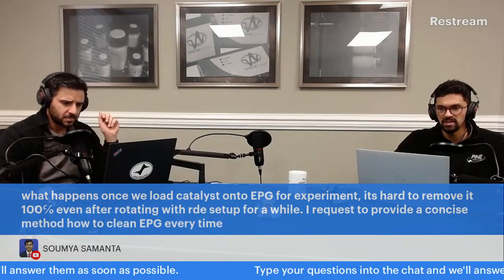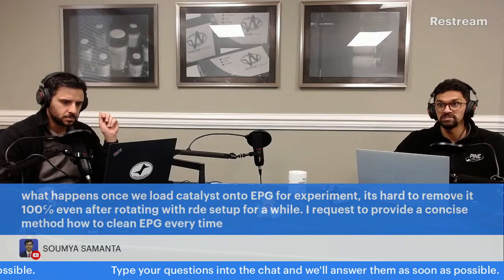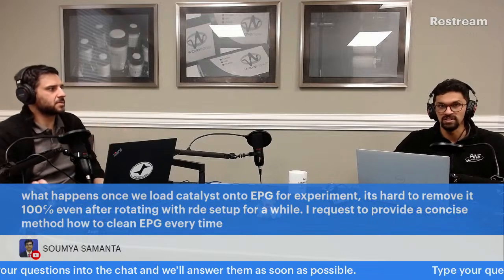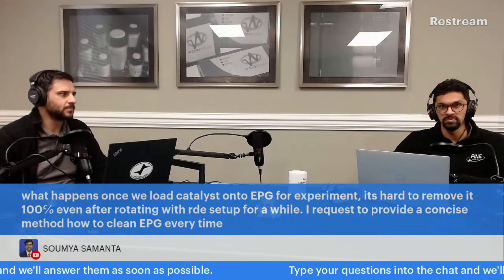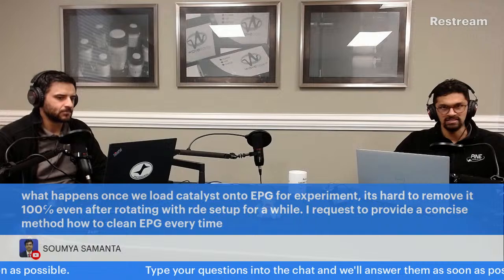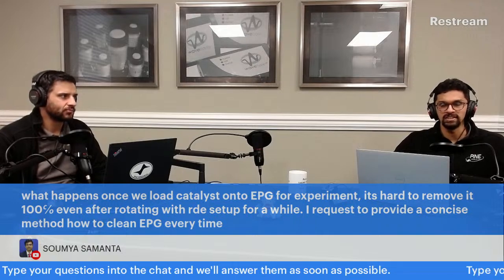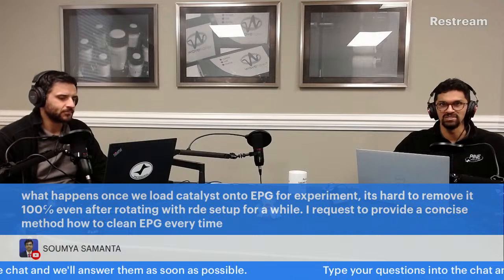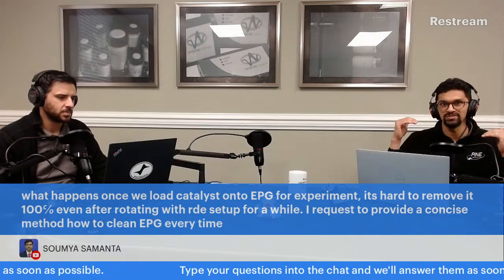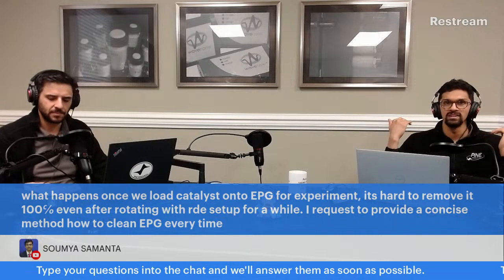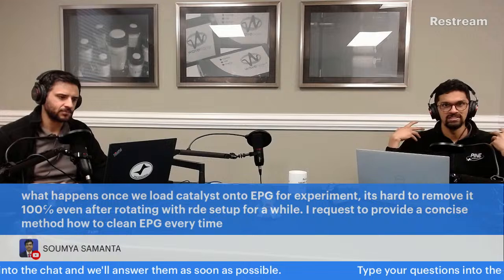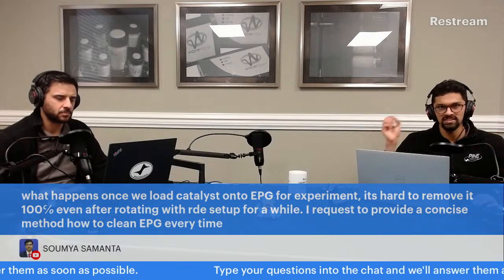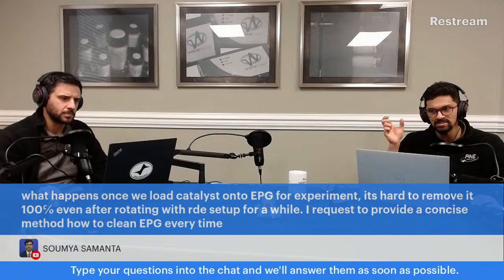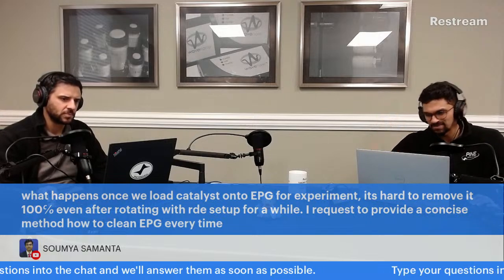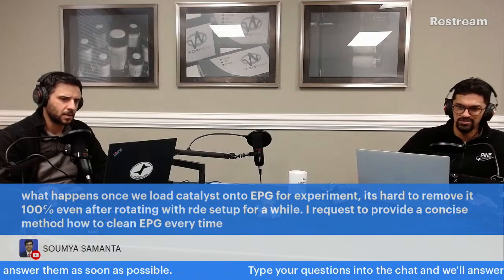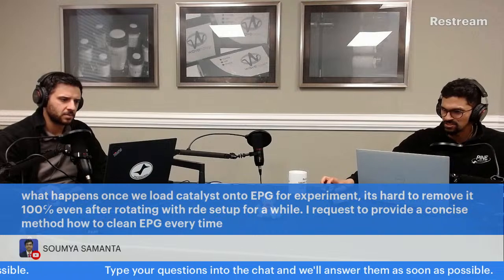Yeah, that might help. But I think electrochemical cleaning will also be very indicative. You're trying to get the same current every time. If you put the electrode in some dilute sulfuric acid and cycle it like 100 times, you'll eventually get a very reproducible surface. That's the main thing, getting a reproducible baseline for your catalyst experiments. So everything that Neil said is going to get 95, 99% of the stuff. And I'd say that extra 1% is just stabilizing the carboxylic acid groups that just got stuck to the glassy carbon, or the OH groups or something like that. That's what the electrochemical clean will help you with.